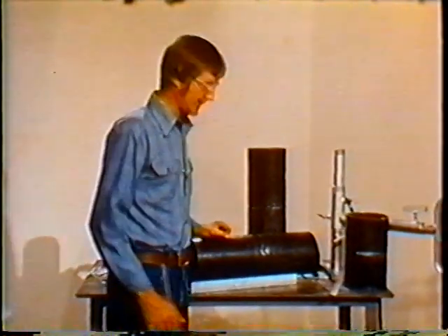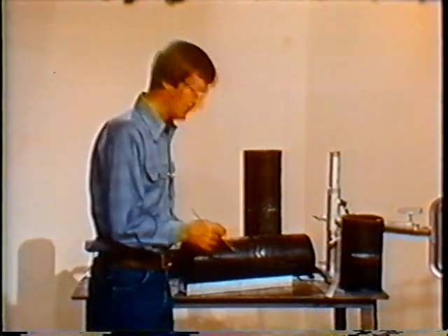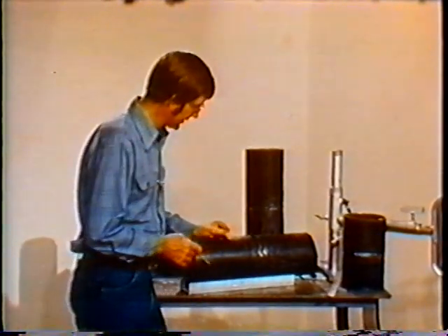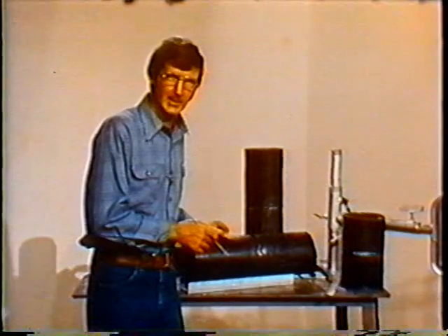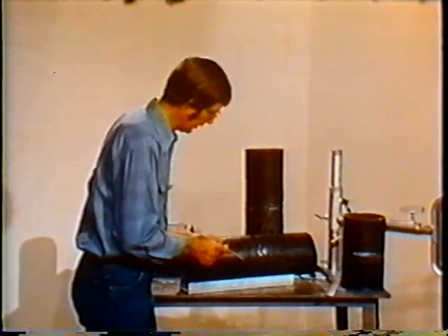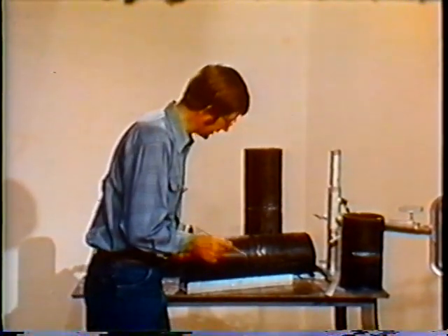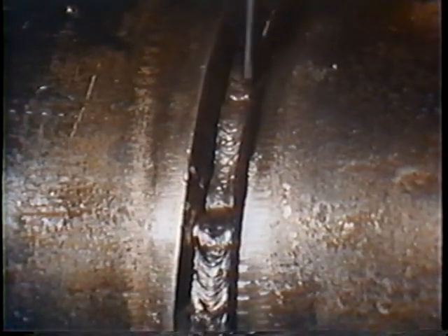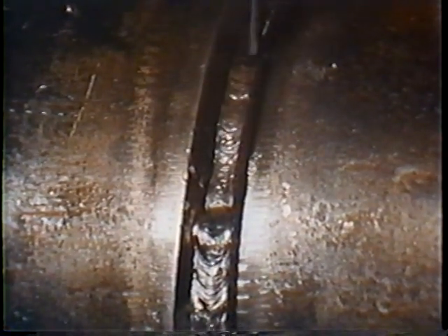We have a completed specimen then of a bead sequence done with 7018 electrodes in the 6G position. We used a total of 10 passes to make this completed weld joint, and we've got one staggered here so that we can talk about them. Here you see the first pass, the root, as it was placed on top of the ring. Notice that it's clean, well fused in on both sides. This is the way we want it, flat.